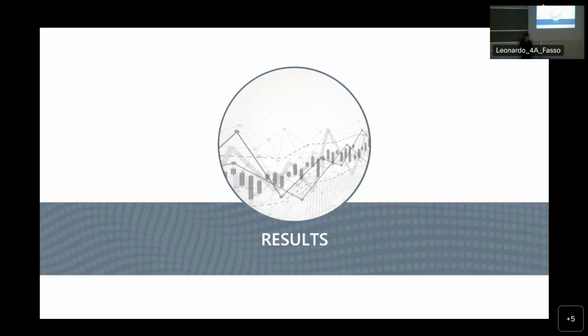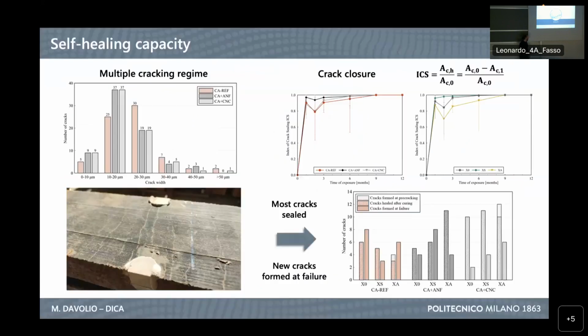Then I will briefly discuss the results of our methodology, starting from the self-healing capacity of our UHPC, which, as you can see, developed a multiple cracking regime with many cracks of a very small width, and this fostered, of course, the self-healing capacity of the material, which is able to seal these small cracks, as you can see from the picture. Most of them are sealed. And this is what we experienced here, when after 9 and 12 months, all the cracks were completely closed. And also, after very short periods, we already are between 85 and 95% of crack sealing.